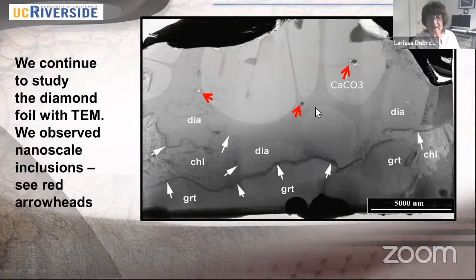So you see here inclusions, right? We observe in this particular foil 3 inclusions. We also observe very well the grain boundary, the boundary between diamond and host mineral. You know that this diamond is sitting, for example, in garnet, okay? But you see here direct contact with diamond. You can study the interface, the atomic setup between diamond and garnet, how they attach to each other. This is the history of growth of diamond.